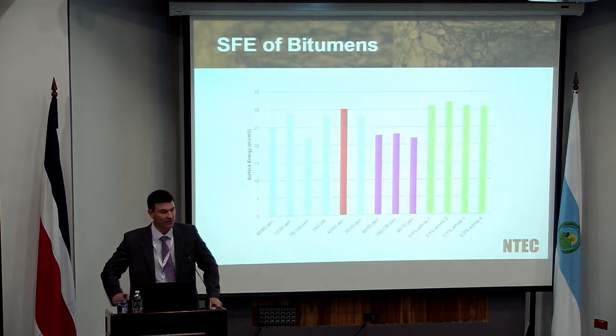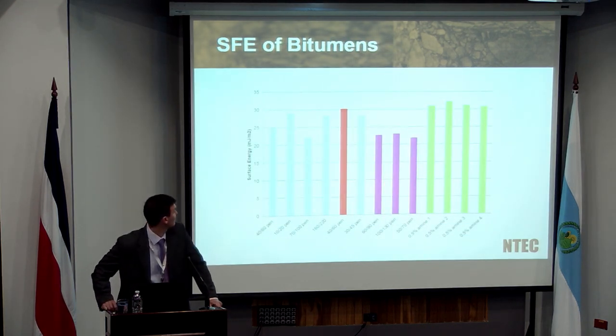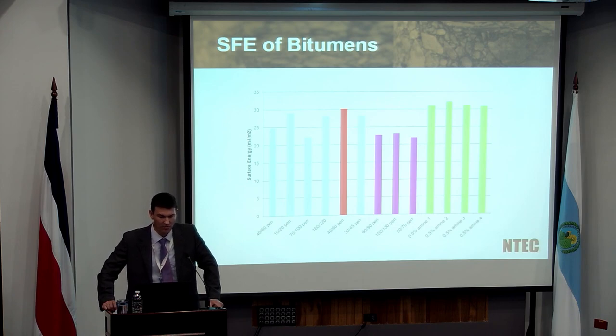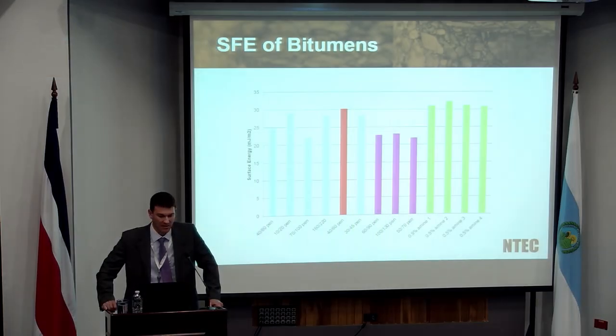So what do we get after we've gone through this process? Well, the light blue curves on the left-hand side, unfortunately, haven't come out that accurately on the screen, but you can pretty much get a feel for the results. And the first thing to say is that bitumen doesn't have a massive difference in terms of its surface energy properties from one source to the other. So this was a sample of about 12 different bitumens. The colors were basically linked to bitumens from the same crude oil source.